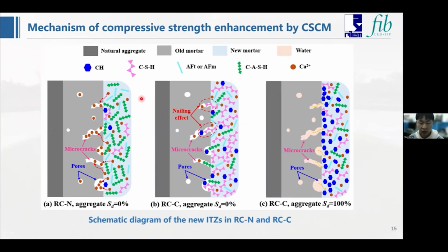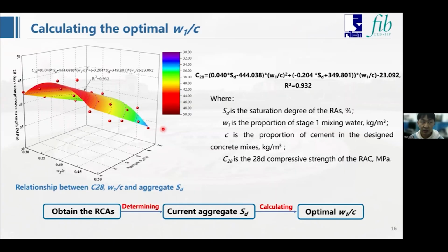However, the increase in aggregate SD diminishes the efficiency of the CSCM because of the water release effect. So we can conclude the two key factors of the CSCM implementing are selecting the optimal water cement ratio and maintaining the aggregate SD at a low level. But in practical conditions, the aggregate SD can vary due to environmental factors. So we establish a formula to calculate the optimal water cement ratio, just as the picture shows.